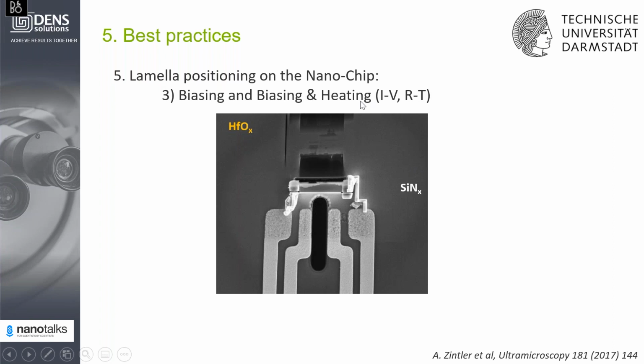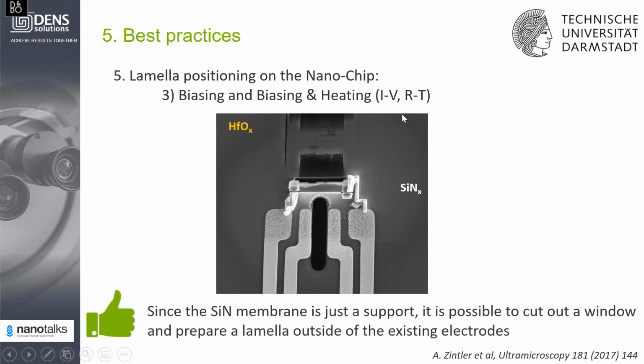For biasing and heating samples, if you don't like to have the lamella on the existing windows, you can actually create your own window outside and put the lamella there. As I mentioned before, our silicon nitride is just a support, so it will not affect any functionality. This is an example of hafnium oxide, a work again from Technical University Darmstadt. The window was milled here, the lamella was prepared on top of our existing biasing electrodes, and then a few electrodes were made with platinum deposition.